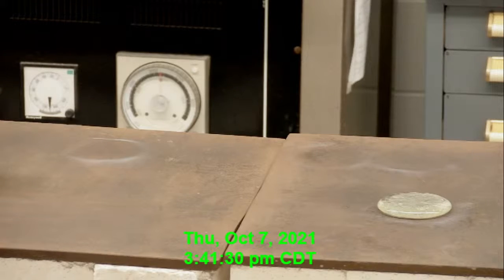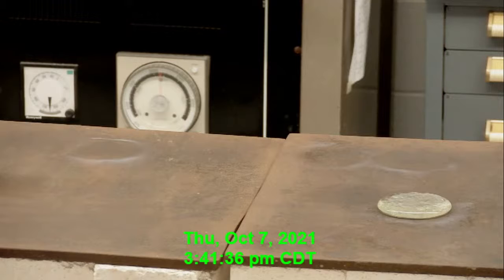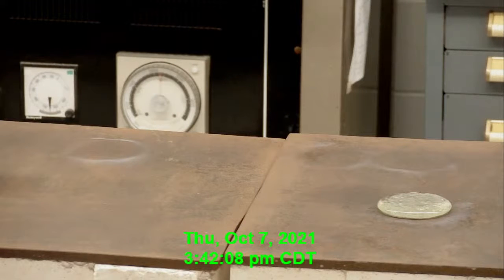We used to have about 2 or 3 crack every time we did this, but I tried to optimize them to be more stable. Sodium glass at 1150, we stabilize it. It really needs to get poured around 13, but since we're making it part of the experiment, it's pouring at 1150 and seeing what we end up with. That's why we're using sodium. I used to do lithium as well, but that's so aggressive it started to soften the inside of the furnace. You'll notice that the top element has sagged quite a bit, and that's likely accelerated by the fact that we used to do lithium glass, and those lithium ions have evaporated, impregnated that wall, and it starts to sag.